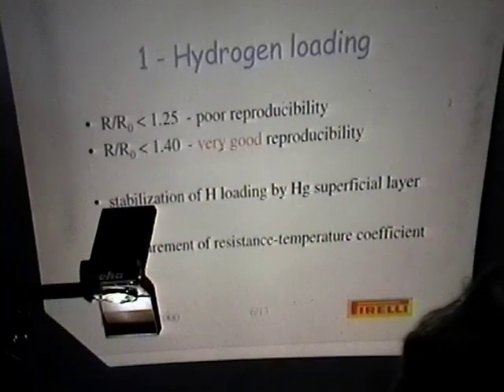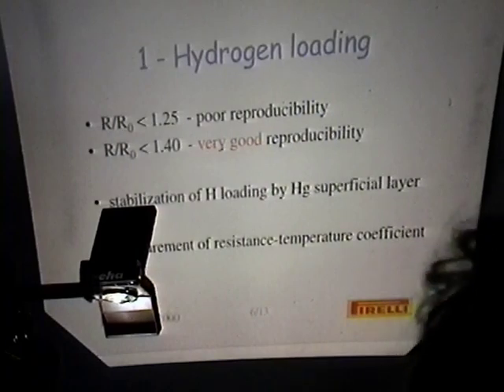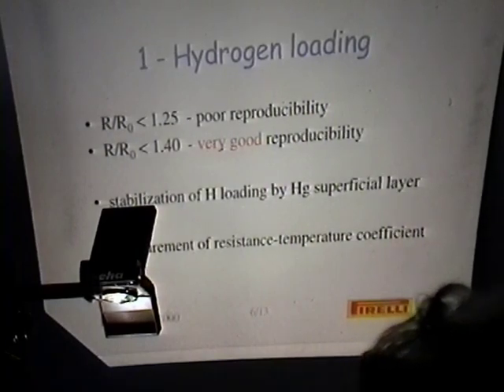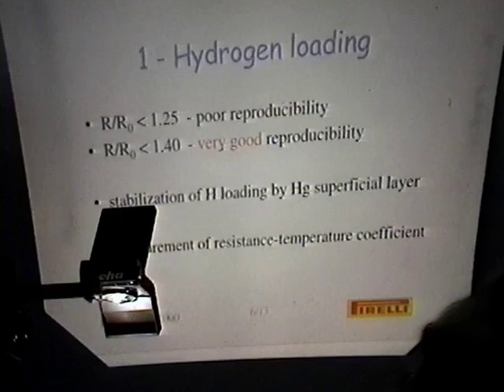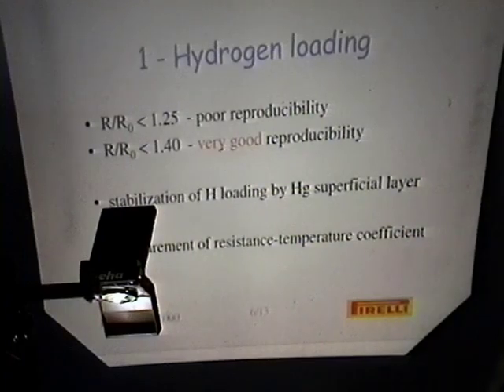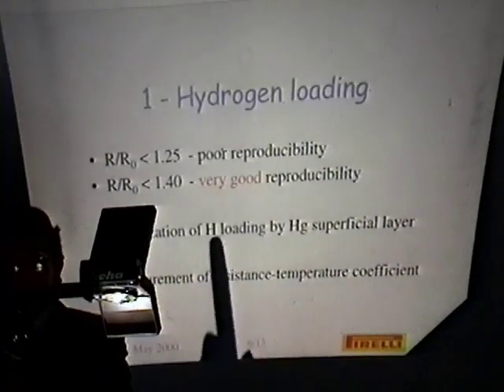The problem is that the limiting value reached is not always the same. It can vary due to the change of experimental condition and probably due also to the characteristic of the wire. The best result would reach a value less than 1.25.